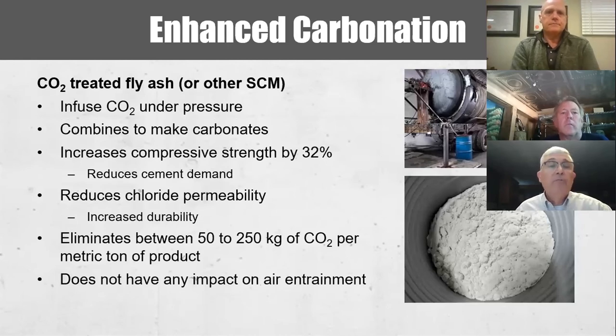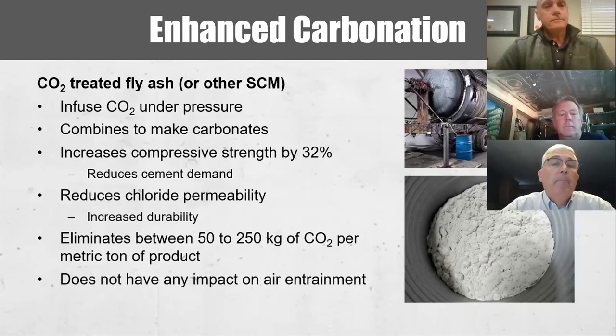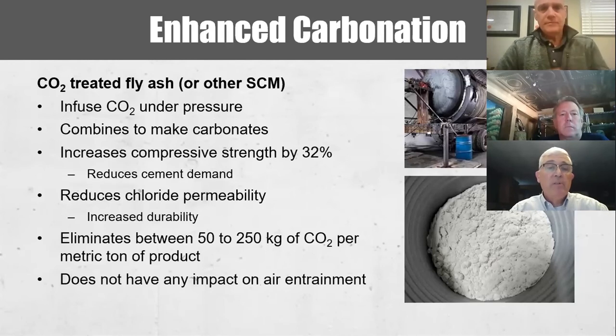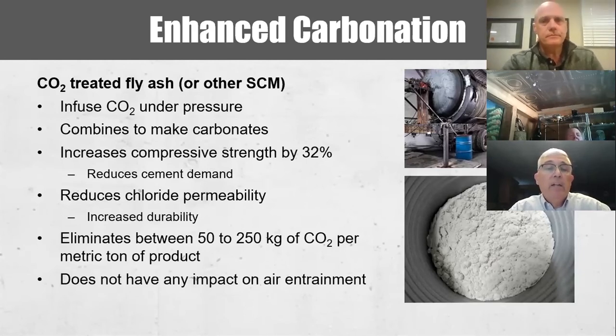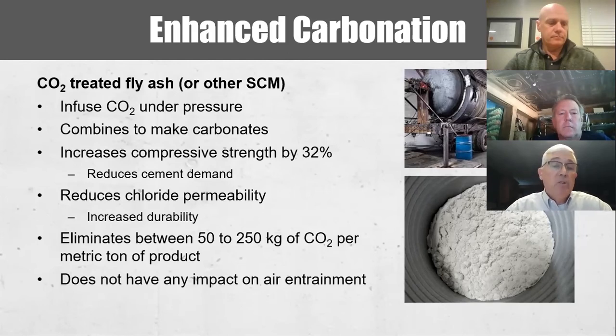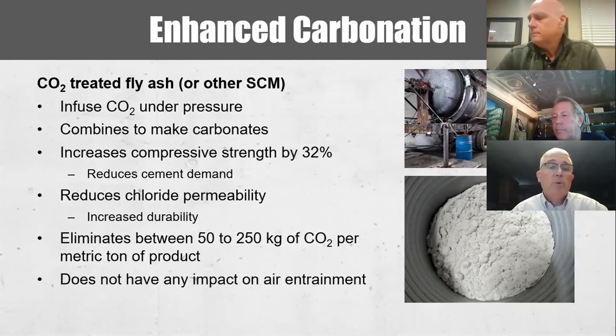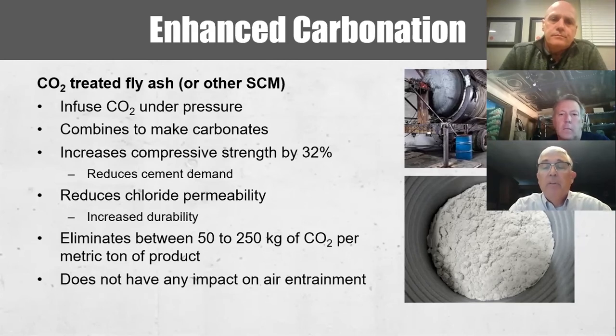Another process is the use of CO2 to treat fly ash or other supplementary cementitious materials. So there's a vessel that's pressurized with, let's say, fly ash, and you infuse CO2 under pressure, and this combination creates carbonates. The developers claim that it improves compressive strength by 32% for the concrete that is then made with this infused SCM material, which then contributes to reducing the overall cement demand. So you're reducing your carbon footprint in that way. It also increases the durability and improves chloride permeability of the concrete that's created. The developers estimate it eliminates between 50 to 250 kilograms of CO2 per metric ton of product that's produced, and does not have any detrimental impact to air entrainment of the concrete that's created.